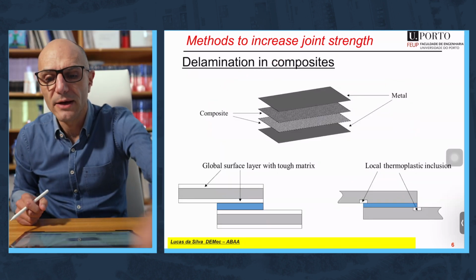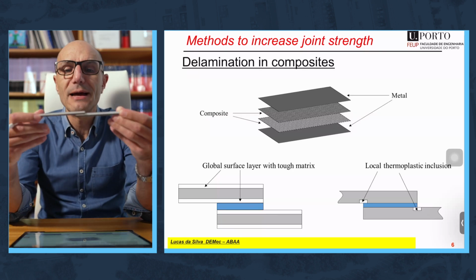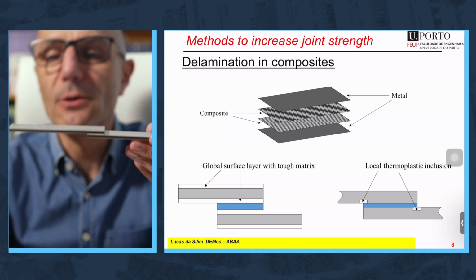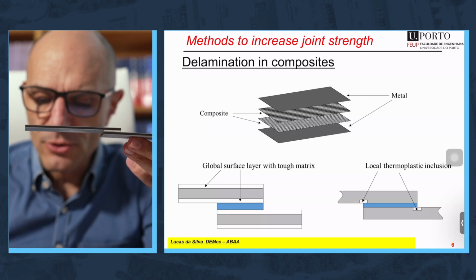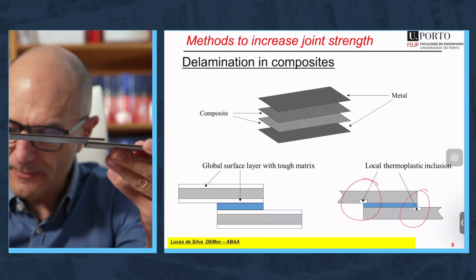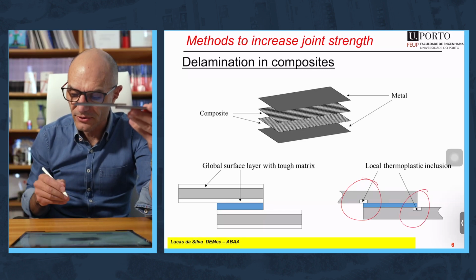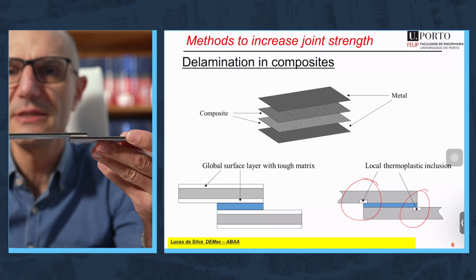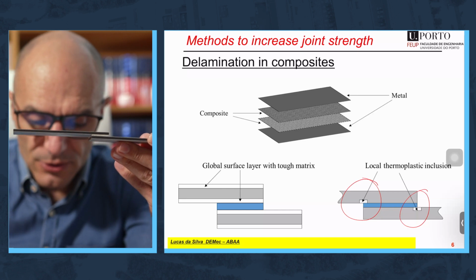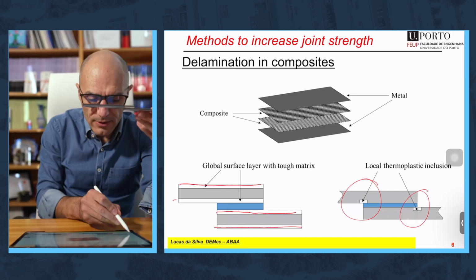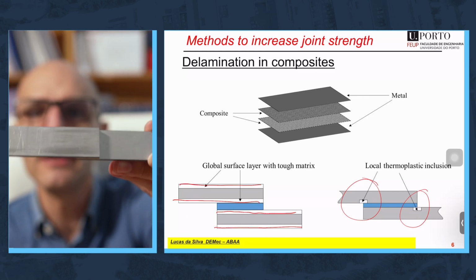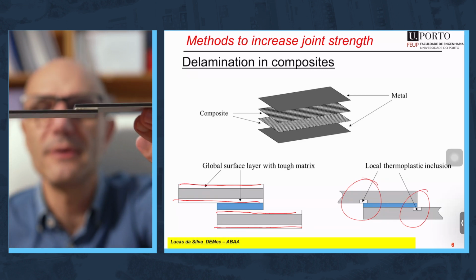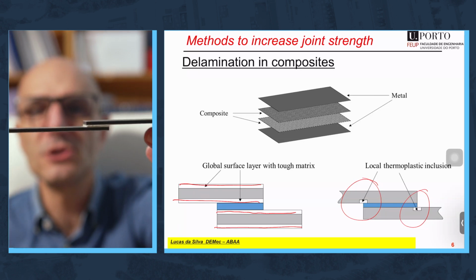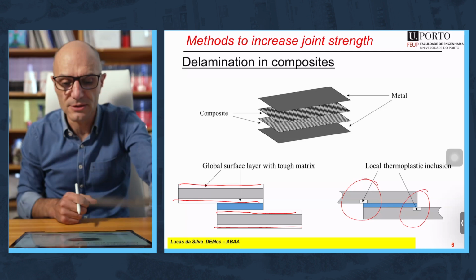But there is still another way you can do, which is using fiber metal laminates, okay? So along the width you are going to use different types of laminates to avoid delamination of the composite. You can do it locally, which is indicated here and here. There are some colleagues from Germany, DLR, that have done that. They surface toughen locally the composite so that it does not delaminate. Here in Porto, what we have done is use a layer of metal all the way through the joint, as represented here. I think it's quite clear. You have on each face of the composite a layer of aluminium which delays the delamination in the composite, and like this you have a much higher joint strength.